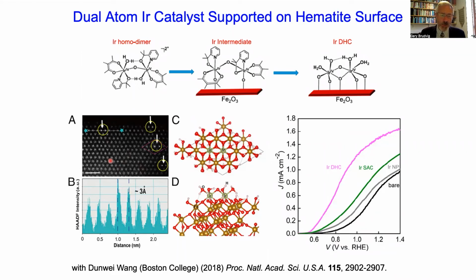And because we can see the lattice, we can model it. So this is Victor Batista's group now. They can model the surface of hematite. And what we find is that the iridium are essentially superimposed over the iron. And this is a position where there are three oxygens on the surface that we believe are coordinating to the iridium in this kind of threefold way here on each of the iridiums. And the structure of the iridium dimer is nicely matched to the lattice structure of hematite, so that the second iridium can also bind to three oxygens on the surface to preserve the structure of the catalyst, which then, of course, remains very active on the surface.